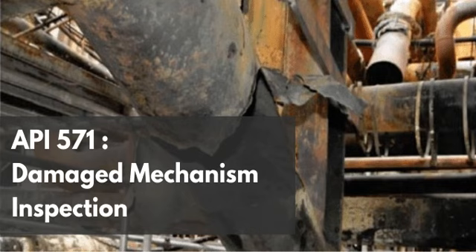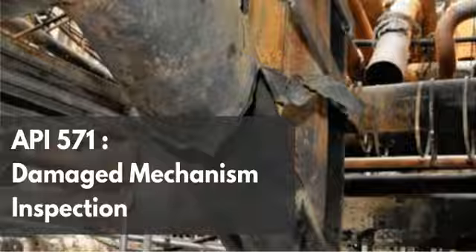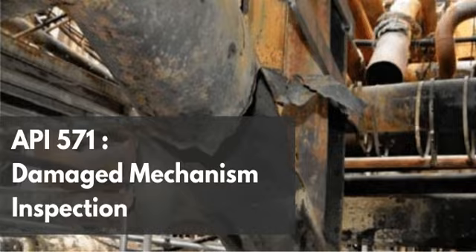Essentially, yes. This goes back to our earlier discussion about the atomic grid. The lattice. Right. At lower temperatures, even at a scorching 900 degrees, the atomic structure of the steel is still relatively tightly packed, and the kinetic energy of the carbon atoms in the gas is simply too low. They just don't have the energy to push in. Exactly. The carbon simply cannot force its way into the solid metal matrix.